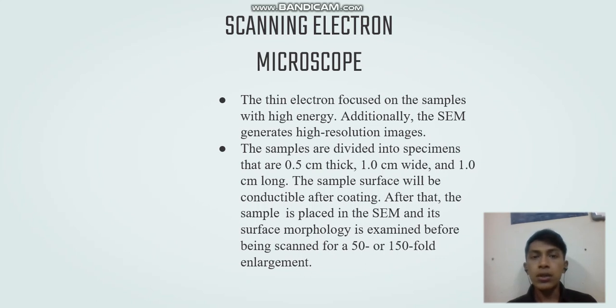Lastly, for the scanning electron microscopic analysis, the SEM means a thin electron beam is focused on the sample with high energy. In addition, the SEM generates high resolution images. So to do this testing, the samples are divided into specimens that are 0.5 cm thick, 1.0 cm wide, and 1.0 cm long. The sample surface will be conductive after coating. After that, the sample is placed in the SEM and its surface morphology is examined before being scanned at around 50 until 150 fold enlargement.